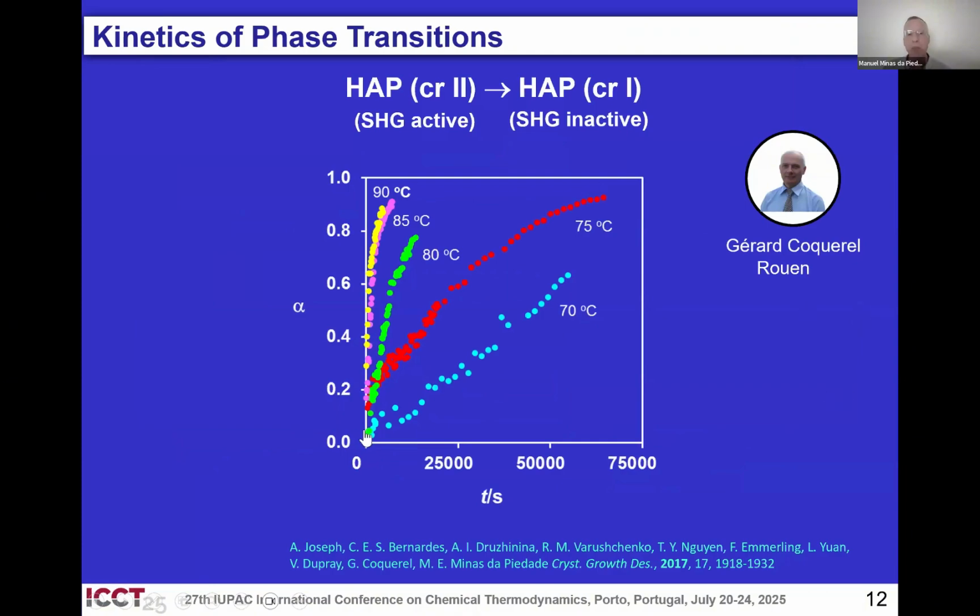And you can see here different kinetic curves that we obtained by looking at the phase transition at different temperatures. This is the degree of conversion as a function of time. And from these plots, you can take rate constants, and you can take energy of activation.